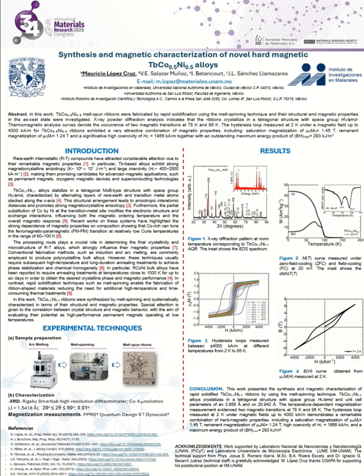Finally, figure 4 shows the BH curve obtained from the hysteresis loop measured at 2 Kelvin. From this figure, a maximum energy product of almost 300 kilojoules/meter cubed was obtained, reflecting a strong hard magnetic character of the rapidly solidified alloy.